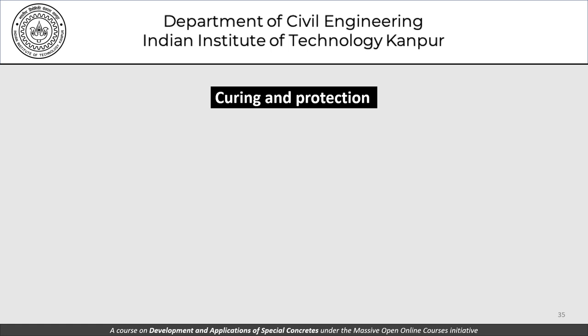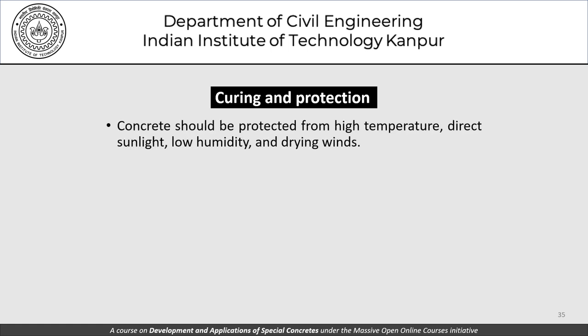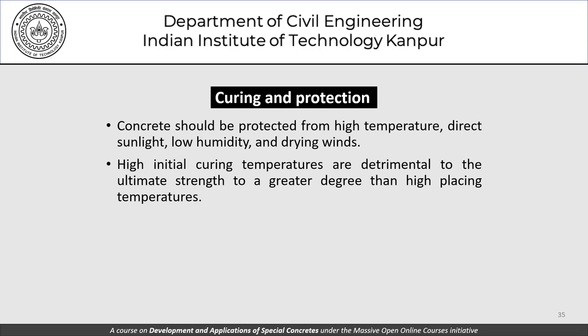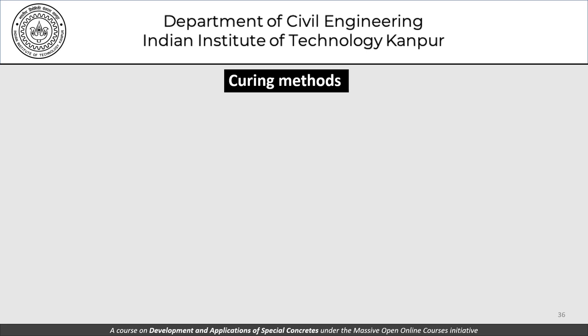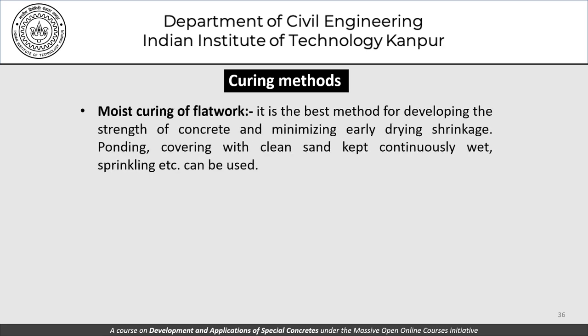Concrete should be protected from high temperature, direct sunlight, low humidity, and drying winds. High initial curing temperatures are detrimental to ultimate strength to a greater degree than high placing temperatures. Concrete should be carefully cured for at least the first seven days, taking special precautions such as covering with waterproofing layers when there is a large difference between day and night temperatures. Moist curing of flatwork is the best method for developing strength and minimizing early drying shrinkage.